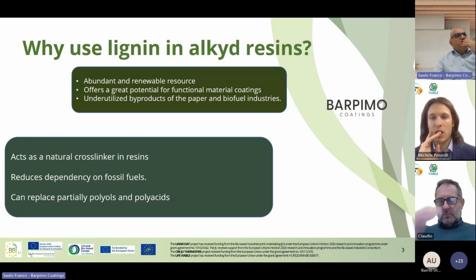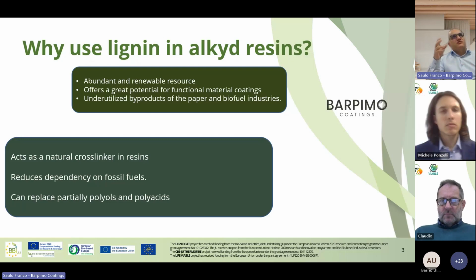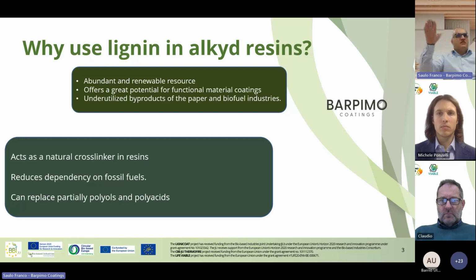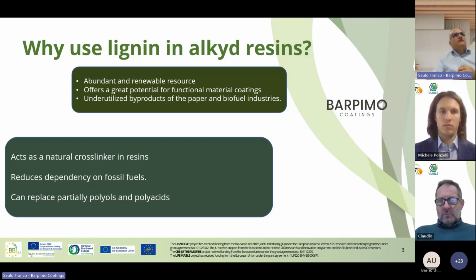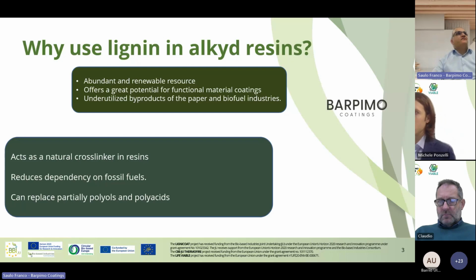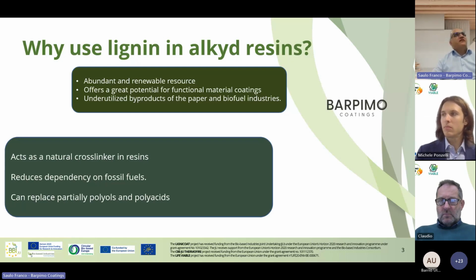Another thing that we consider is that lignin acts as a natural cross-linking resin. As we saw, lignin has a lot of carboxyl and hydroxyl groups, so the material does not stay in the molecule unattached. Because lignin has a lot of functional groups, it can be attached in the molecule of the resin. Another possibility is to reduce dependency on fossil fuels. And of course, in this development, we partially replace polyols and polyacids. Today we'll focus more on polyacids, but it would also be possible to replace polyols.